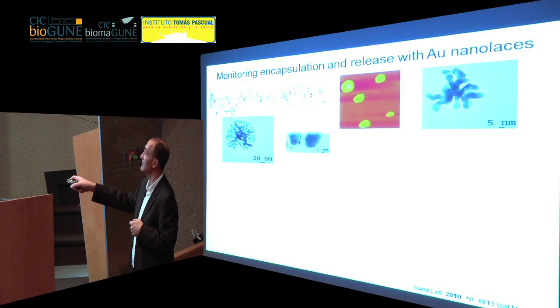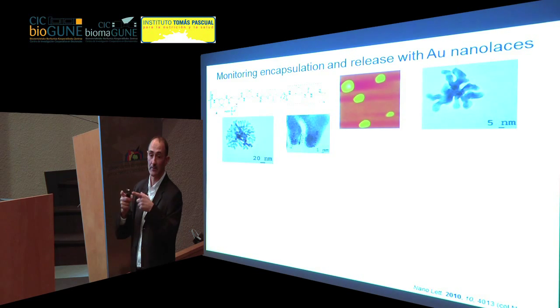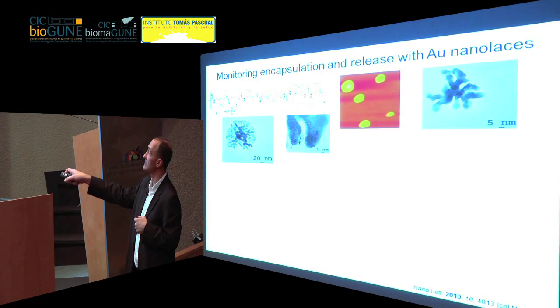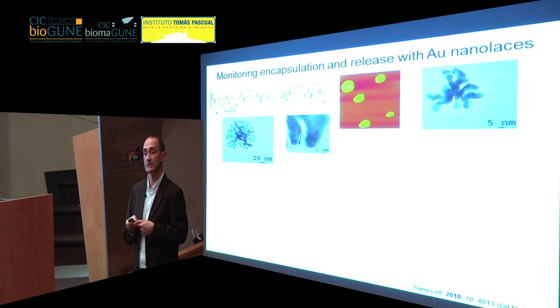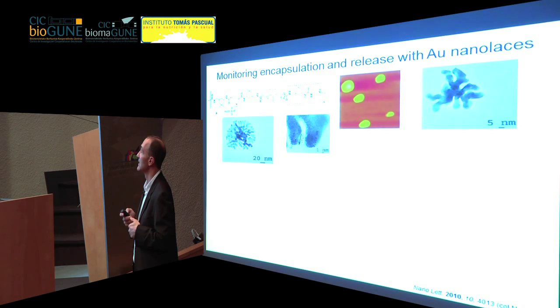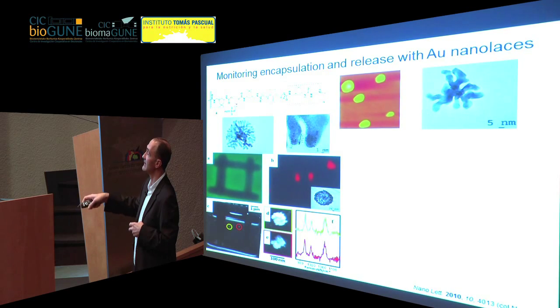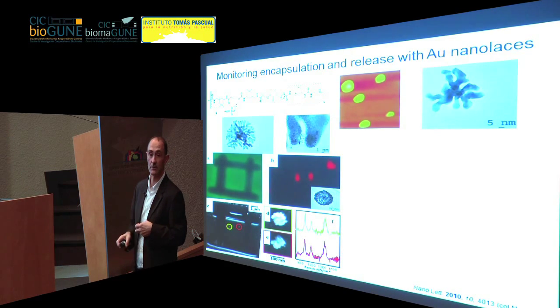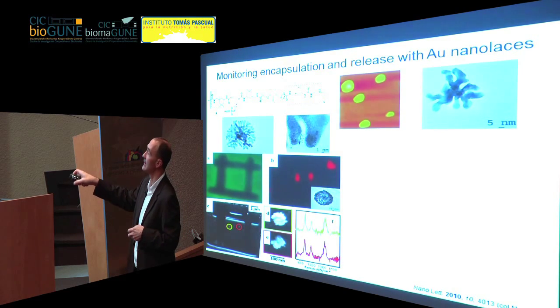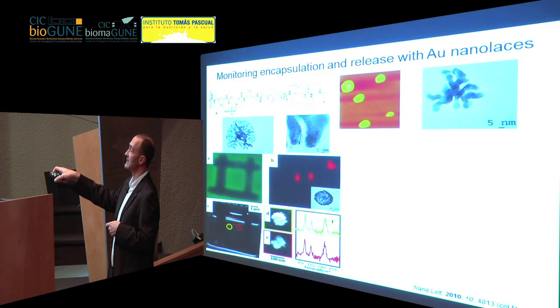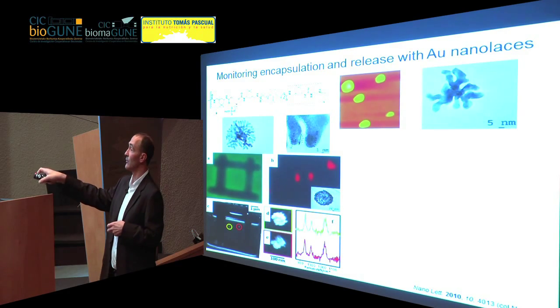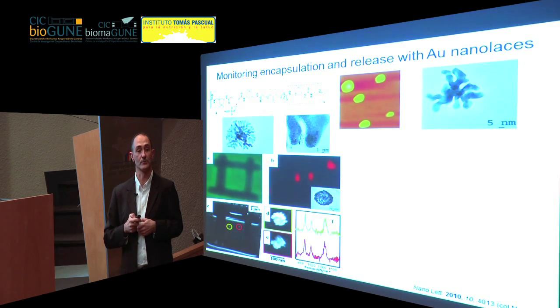However, the nice thing is that they have these very tiny gaps between the branches. So if you're able to bring molecules to these gaps, you may have hotspots there, so you can increase a lot the intensity of the Raman signal from the molecules. So what we did was infiltrate certain molecules in the polymer, and we were even able to identify the spectra from single particles. We labeled a substrate, we went with the confocal microscope, we identified the presence of the particles, we measured the Raman signal from one single particle, and then we went to the scanning electron microscope and identified which particle was providing the signal.